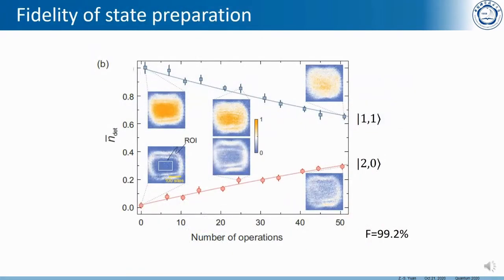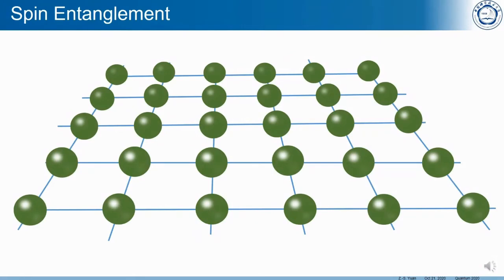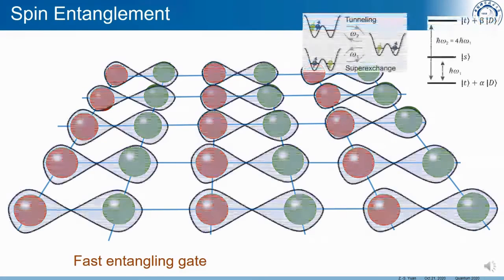In the experiment, we did this adiabatic passage from 2-0 to 1-1 back and forth 50 times, and then we derive the fidelity of this process is 99.2%. Finally, we have a lattice system with unit filling, and based on that, we flip the spin of every second atom. This is the initial state. For the next step, we apply a fast entangling gate.